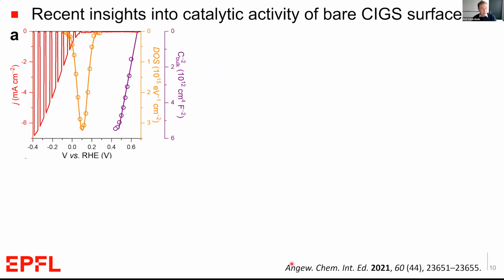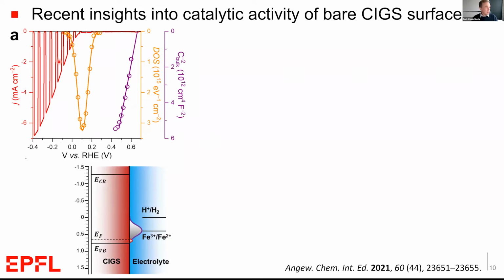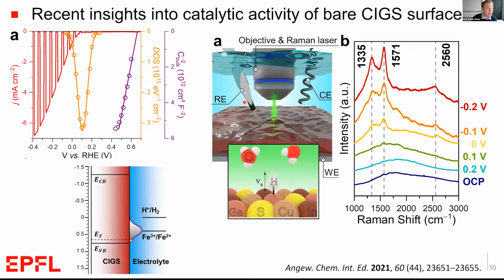And we recently published this paper. I don't have time to go into all the details, but just very briefly, we found using electrochemical impedance spectroscopy a large density of surface states which prevent the high photopotential and limit the onset of the photocurrent in this material. And using other techniques like in situ Raman spectroscopy, we've been able to help to identify these surface states and the active sites for the water reduction reaction directly on this CIGS surface.